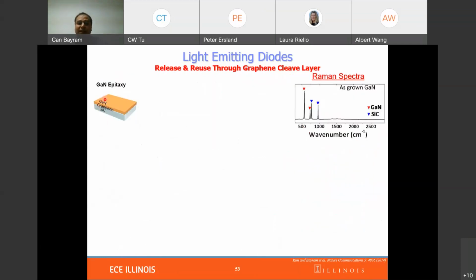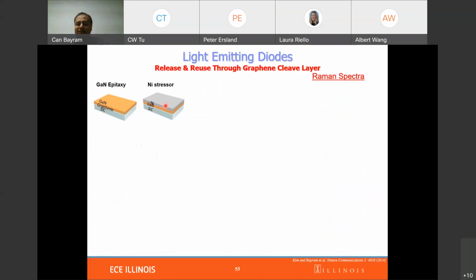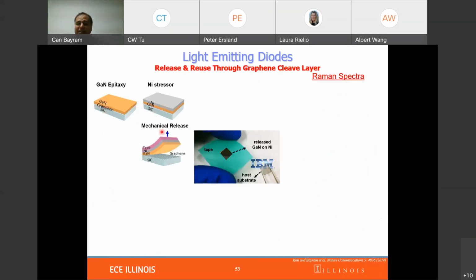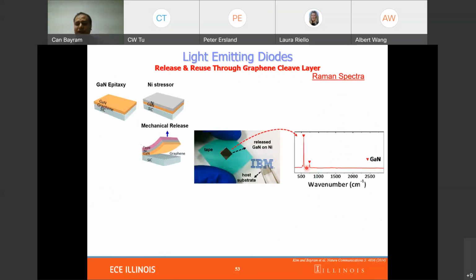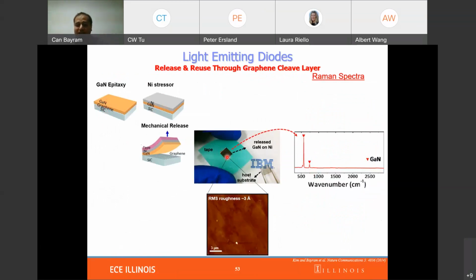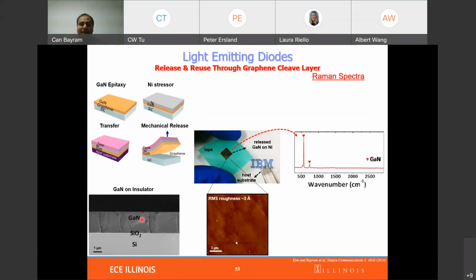Again, we grow GaN on graphene, and then we put our nickel stressor with the mechanical release. We released our GaN, and here is the Raman measurement of the gallium nitride. When we look at the surface, which is basically the growth surface on the graphene, that's the reverse structure, we see that this surface is very smooth. This is not possible by any other technique. And it is so smooth that you can just bond it to anything. Here you can see GaN on insulator, meaning GaN on silicon dioxide on silicon. This is, again, one of the thinnest inorganic structures, and then you can make a lot of different devices similar to silicon on insulator technology.